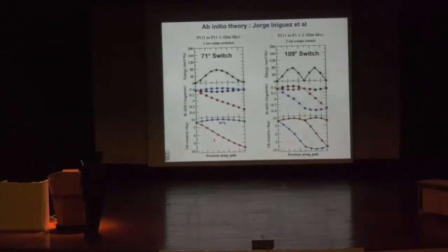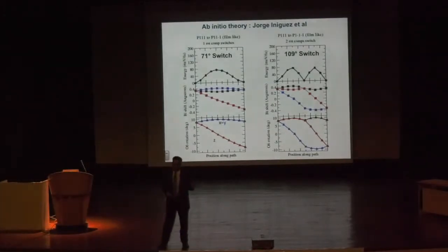Then if you map out for this region, it turns out that a significant, maybe 80–85% of the material switched in a two-step process. And it turns out that was very important because that could give us a pathway by which we could question Nikola's theory. And Jorge did that. What Jorge did was to do ab initio calculation, but his primary claim was, hey, look, when they did the first set of calculations, they did not look at all the ground states. And he said if they had looked at all the ground states, they would have seen other pathways. And indeed, that is true.